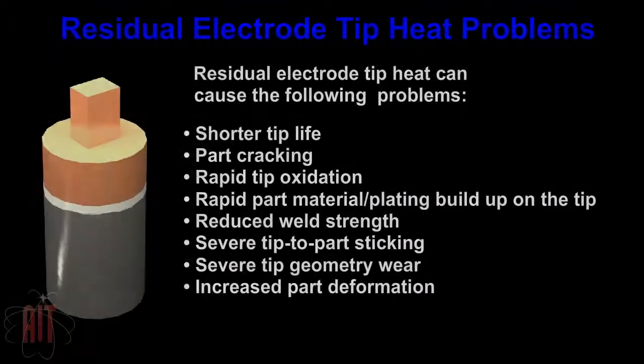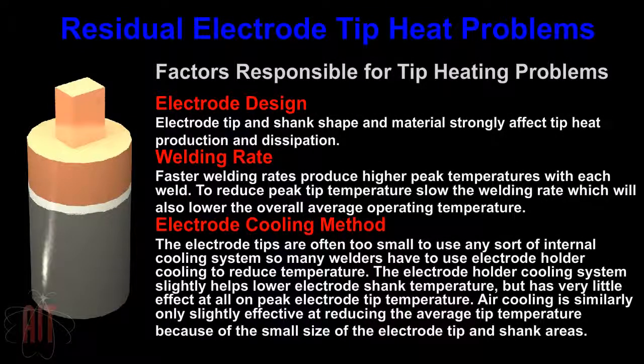Residual electrode tip heat can cause the following problems: shorter tip life, part cracking, rapid tip oxidation, rapid part material plating buildup on the tip, reduced weld strength, severe tip to part sticking, severe tip geometry wear, increased part deformation. The factors responsible for tip heating problems include electrode design, welding rate, and electrode cooling methods.